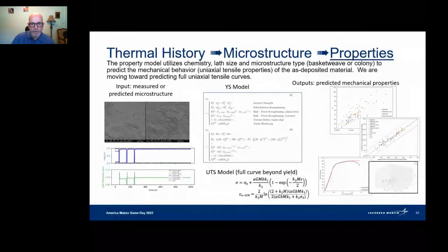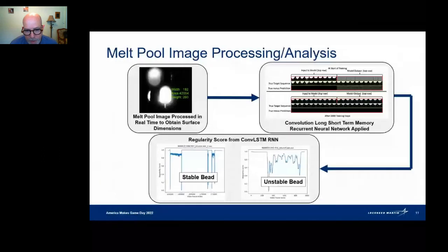Another significant thing that we were able to do, I mentioned earlier that Jack Beuth's team has produced these process maps, and that they were able to predict the dripping boundaries based on contours of the hot wire power and the total power versus the travel speed.